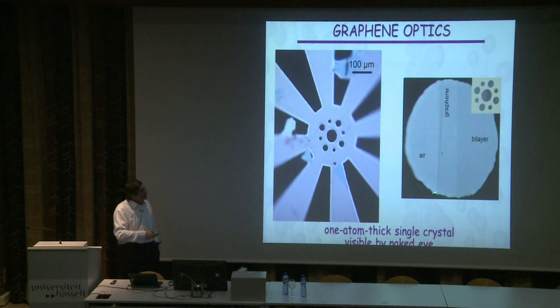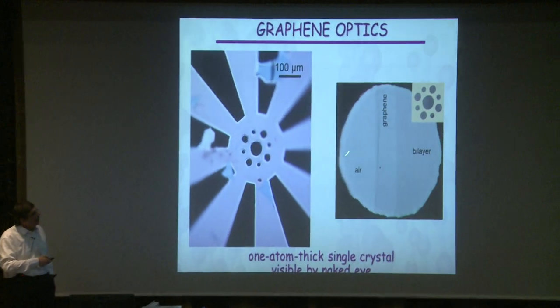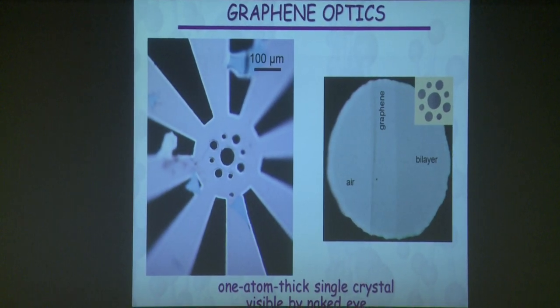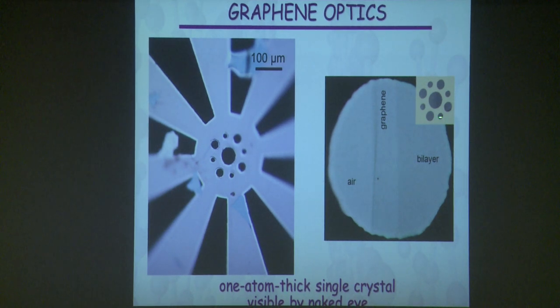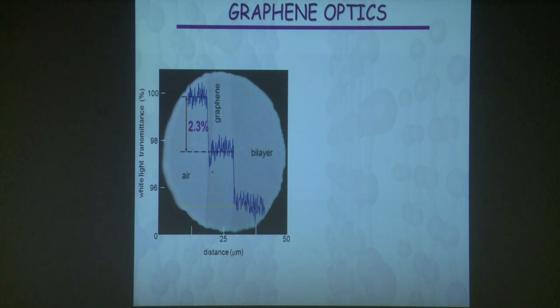So we put graphene, partially covering this membrane, make a small aperture, and look how the light goes through graphene. That's air, light goes through, that's one layer of graphene, this is two layers of graphene, and you see the contrast. This is essentially what you see by your naked eye. These days, when you get these big sheets of graphene, you can do this experiment without much problem. And then where real science comes into play, you not only do observation, you do conclusions, you do analysis. And we find out that the amount of light absorbed is at the edge of our eye's sensitivity. Graphene is gray. It absorbs over all frequencies. It's its color. And the amount of light is 2.3%.